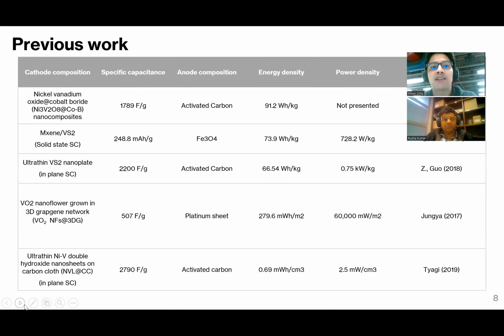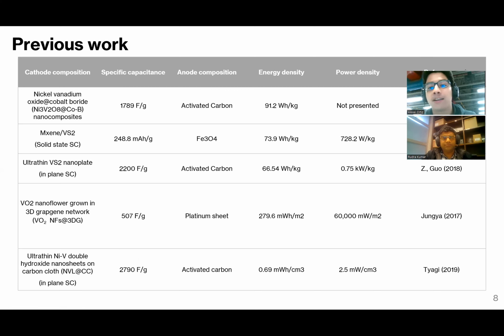Well, now, here is some of the previous work that has been done with materials with vanadium. For example, here we have in the cathode composition a nickel vanadium oxide with cobalt boride in a nanocomposite with a really high specific capacitance of 1,789 farads per gram. That is the usual unit that is used. And as you can note here, in the anode activated carbon is used, as also in the ultra thin nickel vanadium.